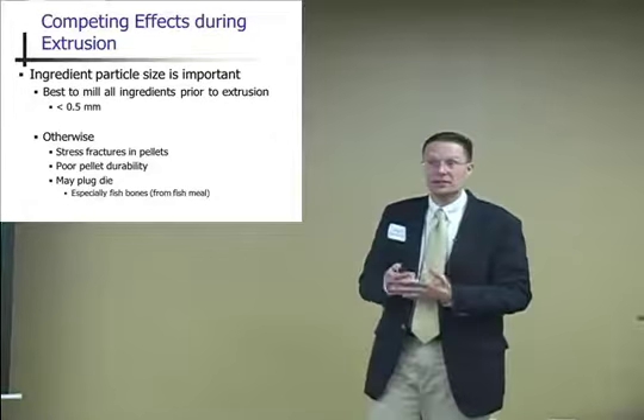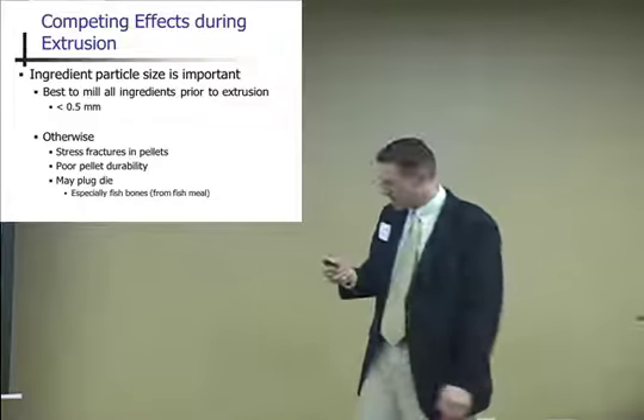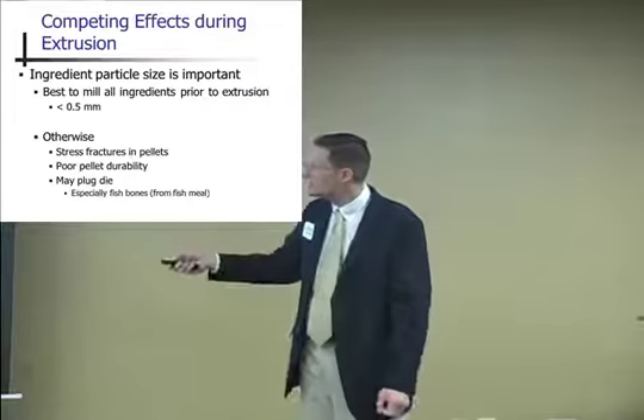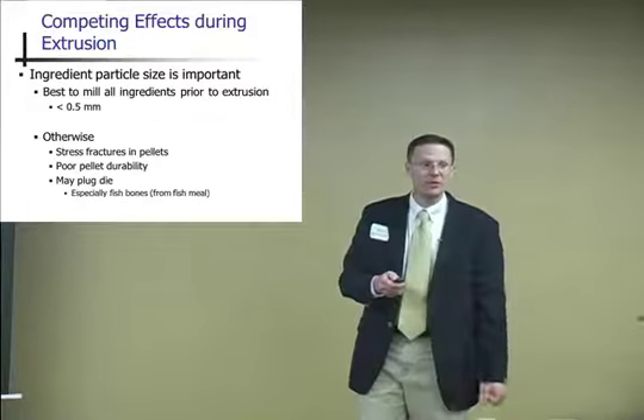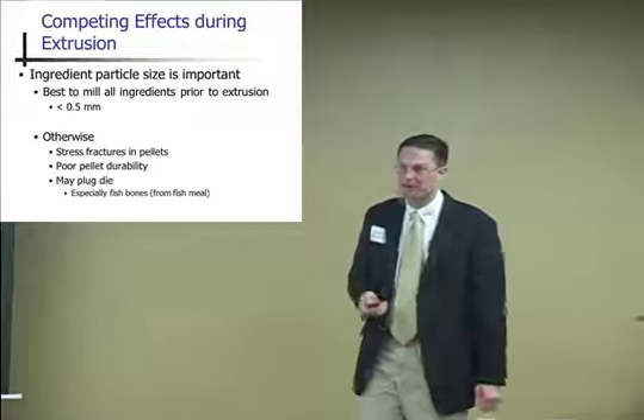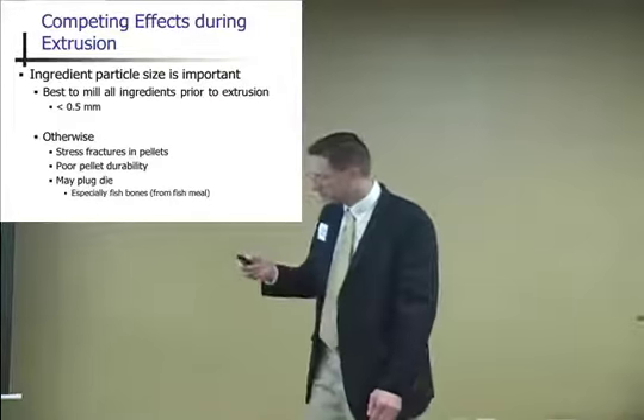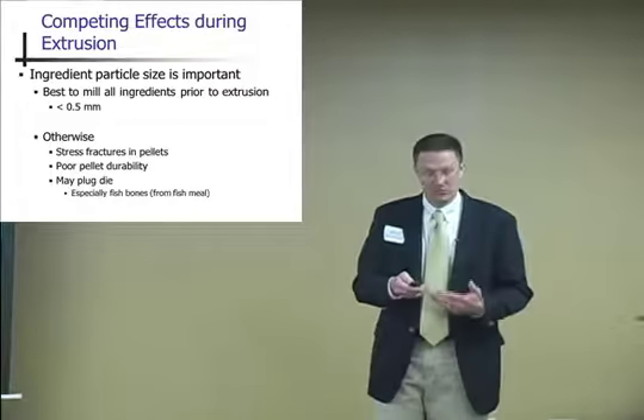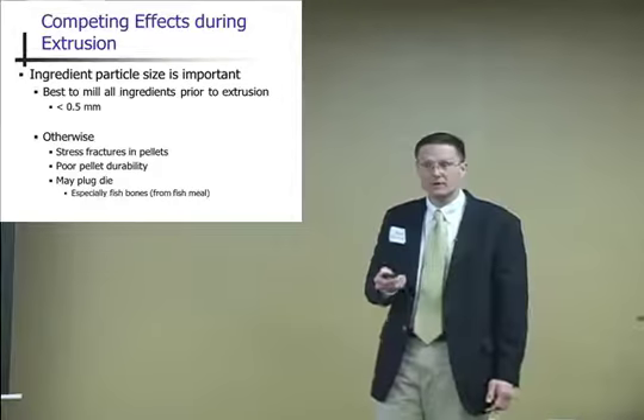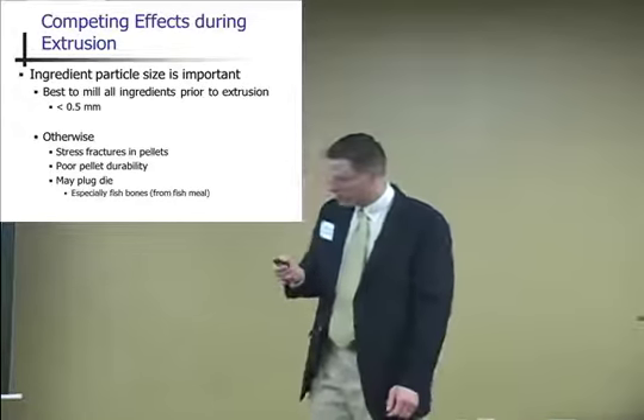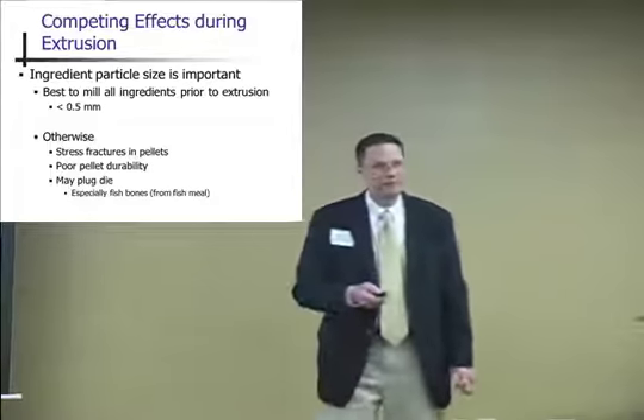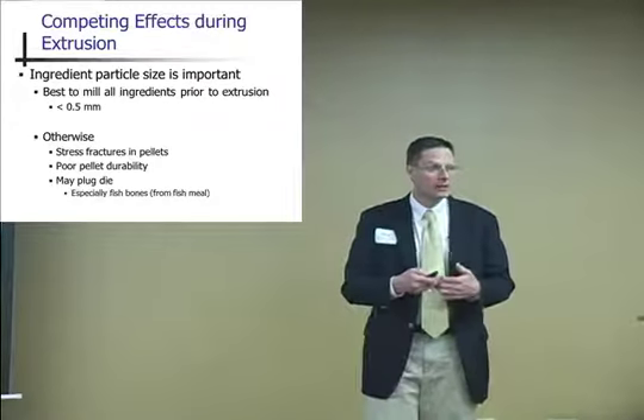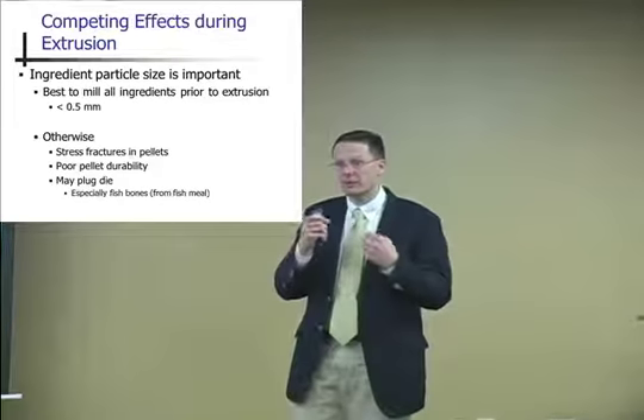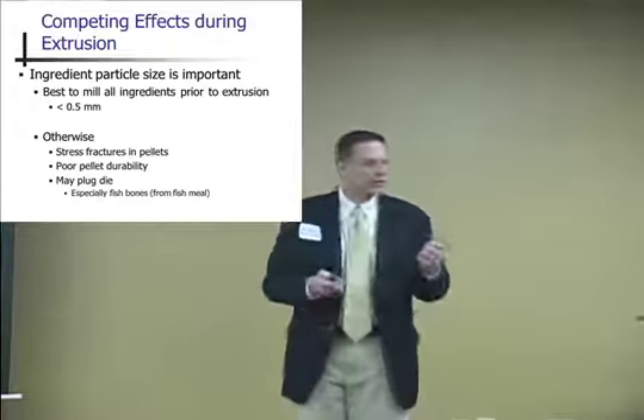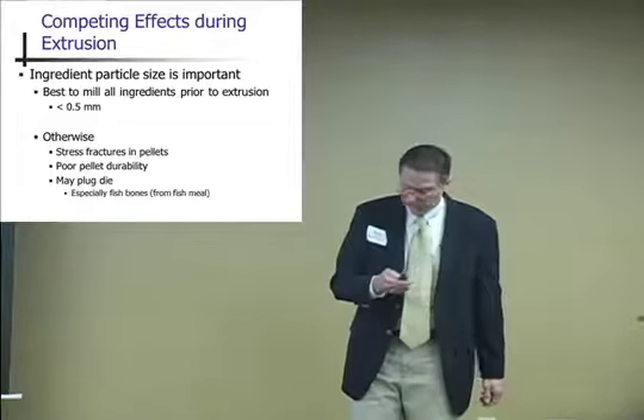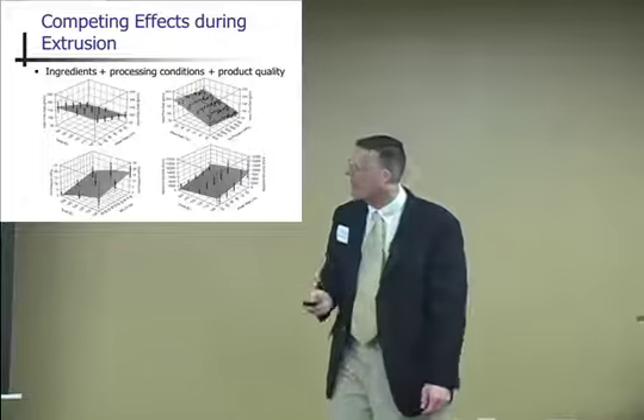Particle size is key. We haven't talked about particle size yet. We talked about the distribution, but if you do a post-mix grind, really you need to have the particle size less than 0.5 millimeters. The smaller the better in terms of extrusion. Otherwise, if you don't grind your ingredients properly, you're going to have stress fractures in your pellets, or the pellets aren't going to bind at all. You're going to have poor durability, or you may plug your die. If you're producing a diet with fish meal and you're doing a 3 millimeter diet, if you don't have your particles ground fine enough, you may plug your die with bone fragments, depending on the quality of the fish meal. So, competing effects.